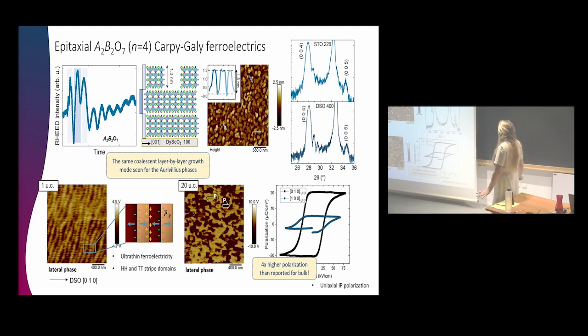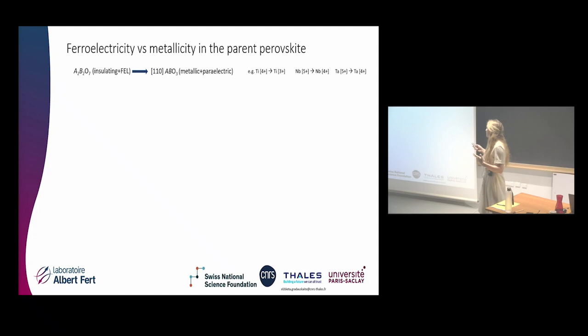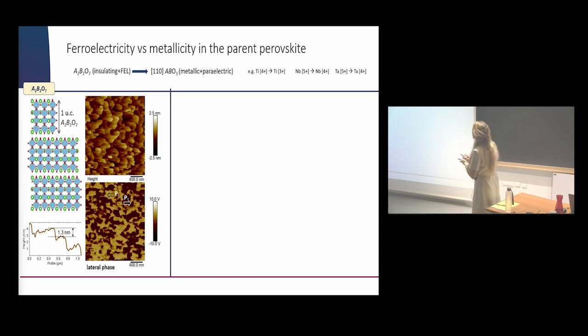So that's already very nice. But now the next step would be to think about this ferroelectricity and metallicity coexisting. So once again, the layered ferroelectric, n equals 4 Carpy-Galy ferroelectric, we know it's insulating and ferroelectric, but its parent phase, 110 oriented ABO3 perovskite, is metallic and ferroelectric. And that's true typically for titanium, niobium, and tantalate compounds. And we can see actually in our measurements that we can have some of this coexistence. So this is a nice film, very, very good quality. We can see that we have these steps that are exactly 1 unit cell height of this big layered material. We can measure that, okay, it's 1.3 nanometers. Nice ferroelectric response in PFM.